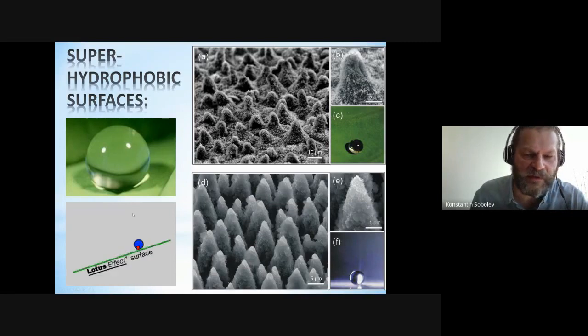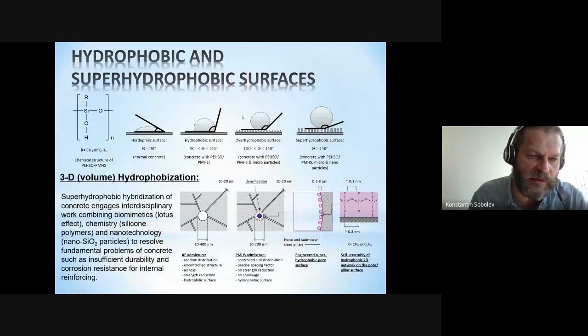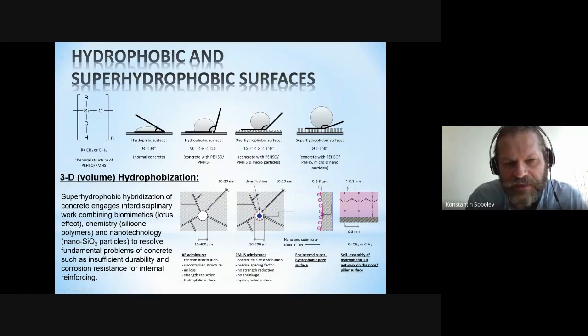So there are a couple of slides. Again, if we can mimic the structure of the lotus leaf, we can produce superhydrophobic structures. Classical concrete is hydrophilic. It absorbs water and also has a very low contact angle, so water easily spreads on the surface. The classical hydrophobic surface is more than 90 degrees, and usually it is impossible to improve it just by surface modification with a hydrophobic agent.